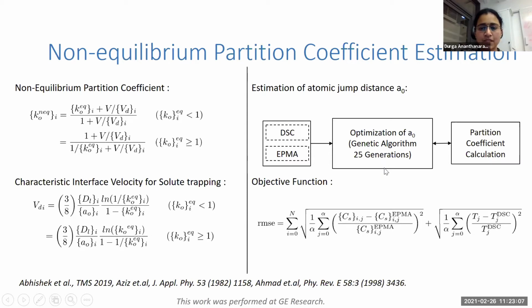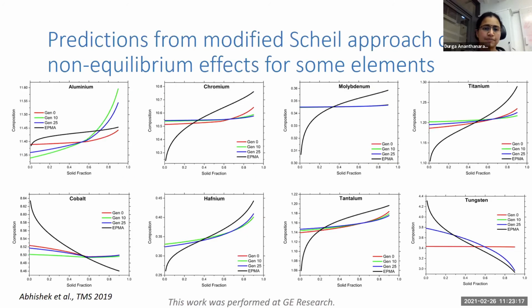Abhishek ran this genetic algorithm and then tried to get closer to the experimental data. And this is what we had. After 25 generations of this calculation, we see that for some elements, the black curve is the EPMA data and the blue curve is the final generation 25 prediction from the model. So we see that for some elements, we are getting closer, but not for all. But overall, we at least have similar trends in the direction of segregation for most of the elements. So some more improvement can be done here. But the first cut is, of course, that we need to include the non-equilibrium effects when we calculate segregation.